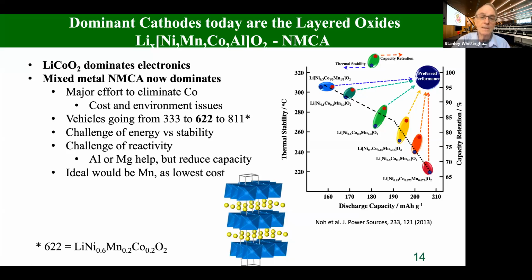So all these materials, if you pull out all the lithium, are metastable at room temperature, and if they get warm at all, will evolve oxygen. So let's look at the most stable one of this. This is 1/3 nickel. This is stable to about 310 degrees centigrade. It only stores 160 milliampere hours per gram. If you go to 85% nickel, you're approaching 210. But now you see